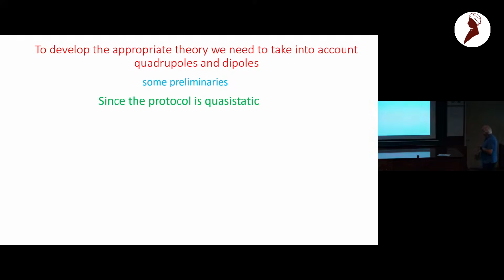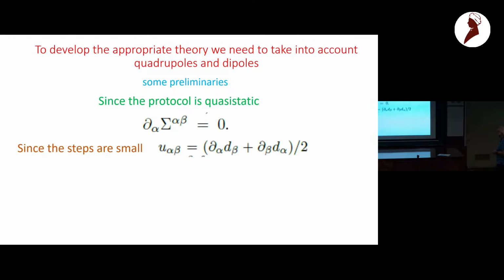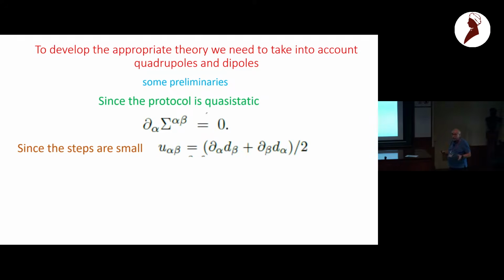Since the protocol is quasi-static, now I have to add some things in order to tell you how to do a theory of all this. So some preliminaries. Since the protocol is quasi-static, the stress that we are building behind when you do this step-by-step thing is divergenceless, because you do bring the system back to mechanical equilibrium after every step. This is important, and this was not used in previous theories that we've done when we didn't look at accumulated stress. Since the steps are small, we are going to assume that the relation between the strain field and the displacement field is still linear. That would be untrue if the system is brittle.